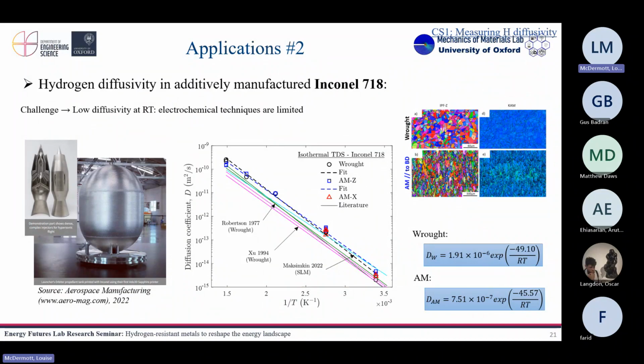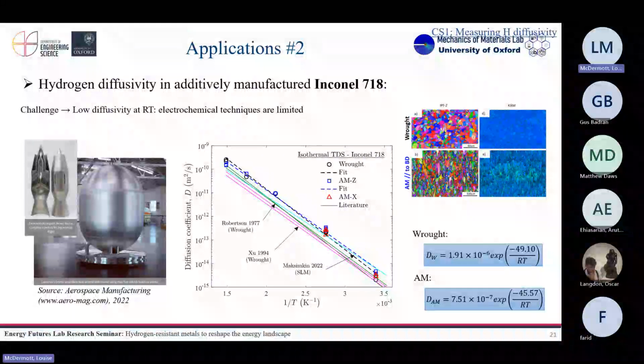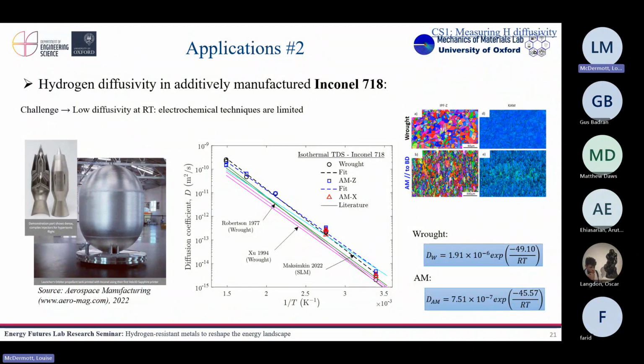Unlike permeation, you are not limited by the boiling of the solution, because in permeation you can do the test at higher temperature, but above 70 degrees everything becomes very tricky. So we managed to calculate the diffusivity of different Inconel grades at a very wide range of temperatures, which is very useful to know the diffusivity in real applications. For example, imagine you have a blade of a turbine that's going to work at 500 degrees. Then with this technique, you can know the diffusivity of hydrogen at that temperature.